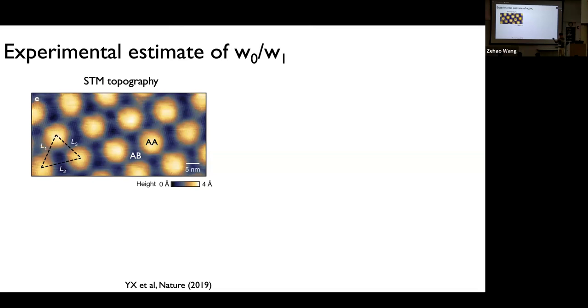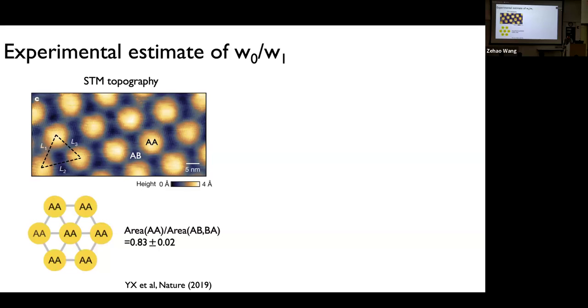And then you have the AB region. And then in practice, depending on the angle, etc., and the relaxation, the area of the bright spot would be very different if you had different relaxation. So one way to approximate this, or extract this, is just to take the area of AA divided by the area of AB and BA, which is the dark spot, and then you can get a number. And then our estimate was 0.83.